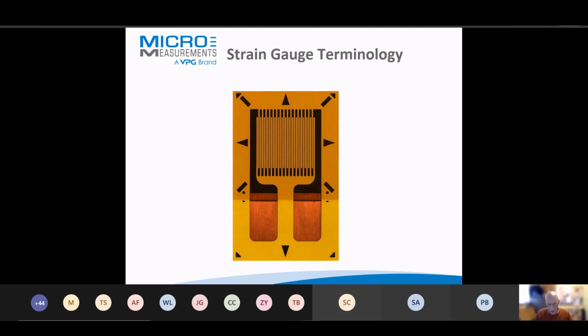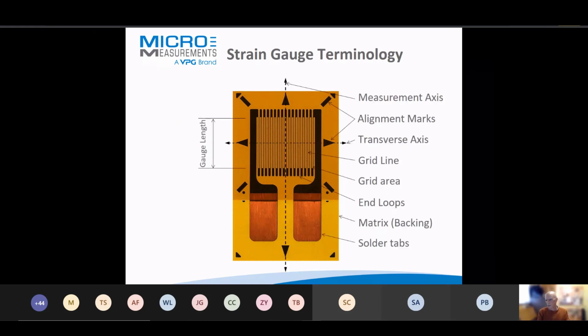Just a bit more of a close-up here, and there's a few more bits of terminology, and I don't really have time to go through all of these. I've been timing this, but you can look at this at your leisure at a later time. This just shows another close-up with some of the terminology. We have here the gauge length. So when we talk about a 6mm strain gauge, we mean that the length inside these end loops here is 6mm. The strain gauge measures average strain in the grid, and it measures strain in the direction of the grid lines. And that's why we have these very distinctive alignment marks, so we can position the gauge accurately to take the measurement that we wish to take.